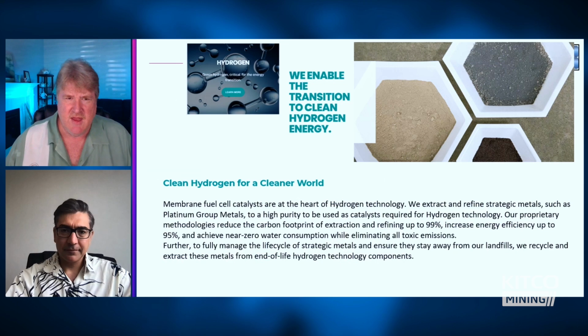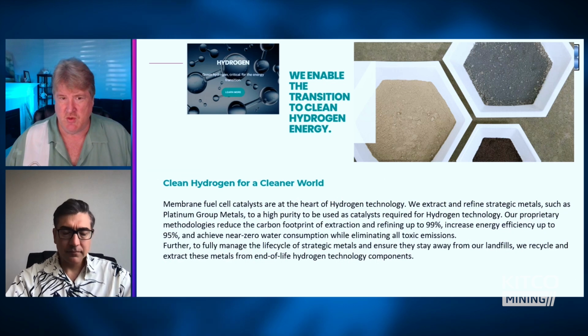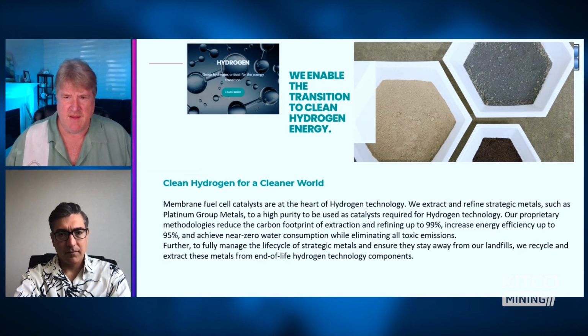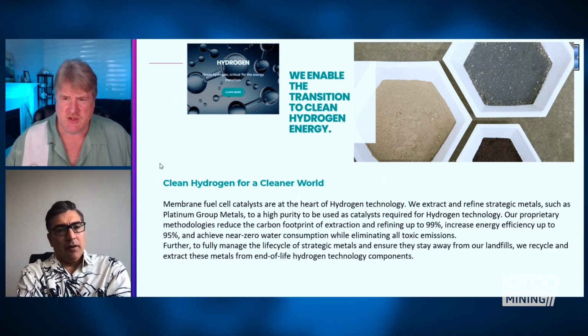Okay. And then the last of the four buckets that you deal with, you mentioned hydrogen, and presumably here you're talking about PEM fuel cell stacks, for example, used in transportation that have platinum, a little bit of iridium, and potentially some ruthenium in the mix, or electrolyzers, which are very much iridium dependent with a little bit of platinum and ruthenium again. So three very specific PGMs. Is that the streams that you're talking about as feedstock from the hydrogen economy?